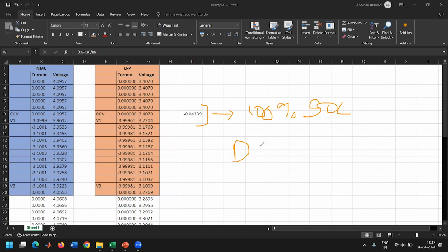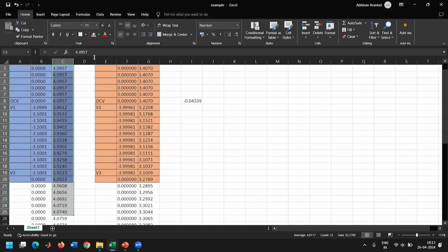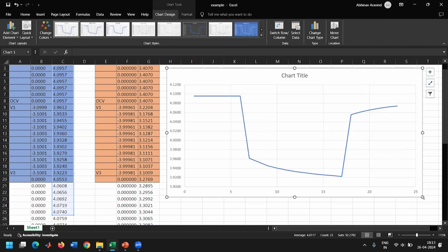After I fully charge the cell, I can perform a pulse power characterization, or also what is called a DCIR test. In that test, they will be loading the cell with many pulses of current. And in each pulse, the voltage response will be recorded. Okay, so the voltage response actually looks like this. For one single pulse of current, the voltage response looks like this, then for multiple pulses, how will the voltage response look?